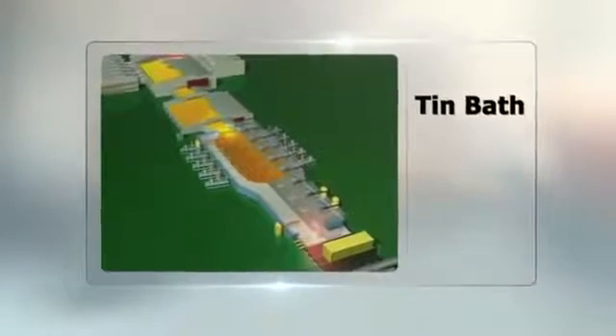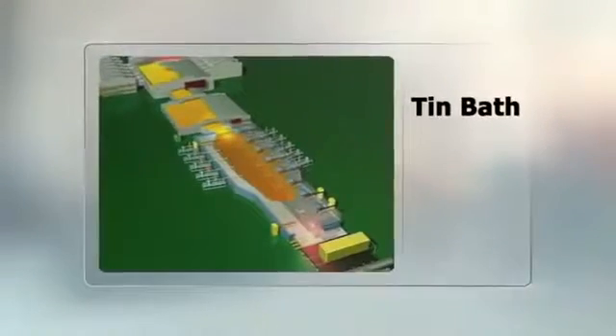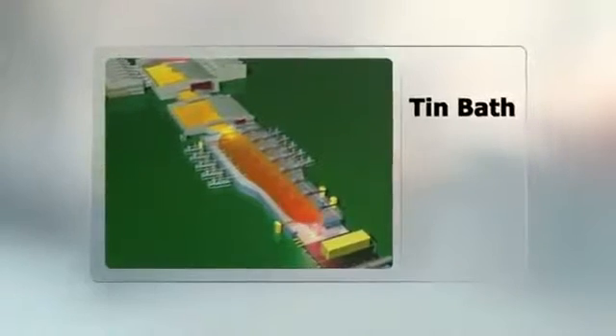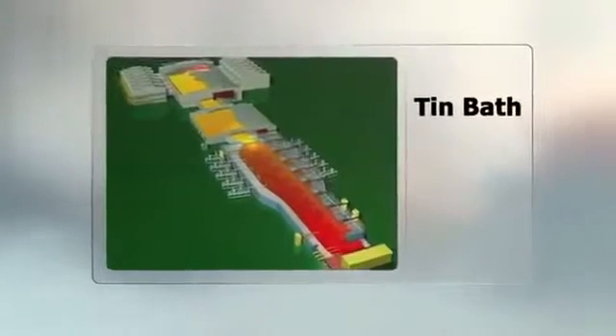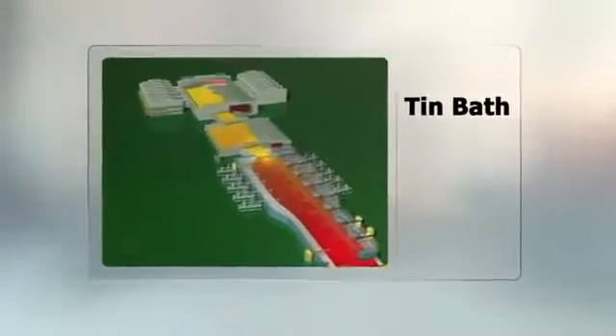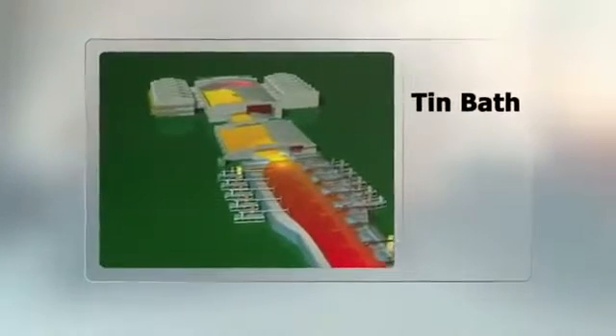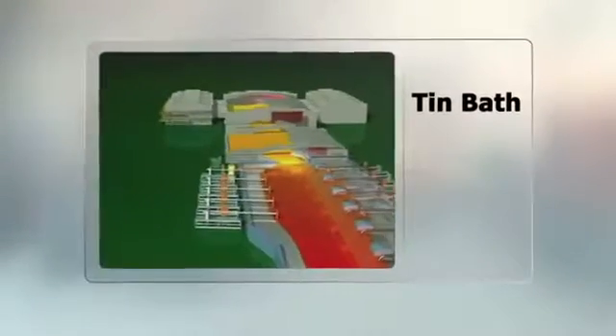Molten glass enters the tin bath and floats on top of the more dense molten tin, like oil floating on water. Here, the glass spreads out, following the perfect flatness of the tin, so that the upper and lower surfaces of the glass remain absolutely flat and parallel, with perfect spectral properties.